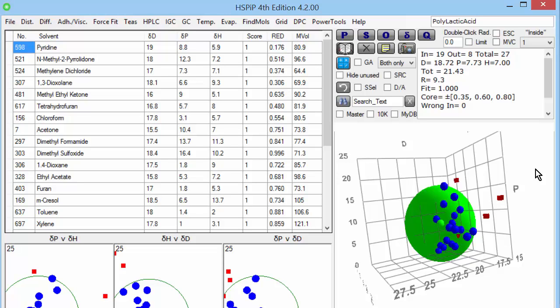And people say, well, how much should I use? How much polymer should I put in the tube? How much solvent should I add? The answer is that there is no answer. If you have a high molecular weight polymer, then it's unfair to ask it to form a 10% solution, so you have a rather small amount of polymer and a large amount of solvent. If you have a very low molecular weight polymer, which is highly soluble in lots of things, it would be rather stupid to have a small amount of polymer and a large amount of solvent.